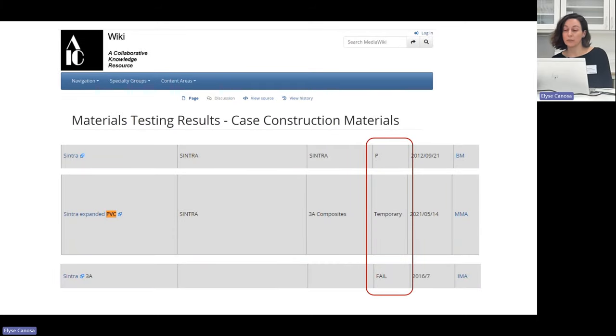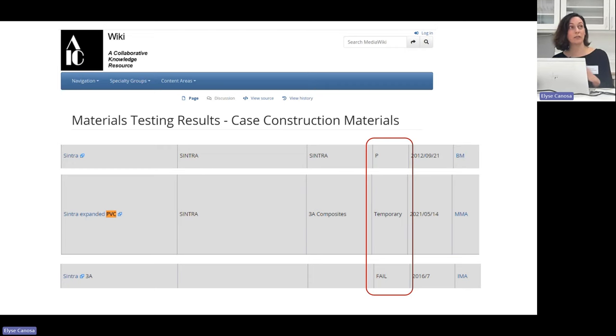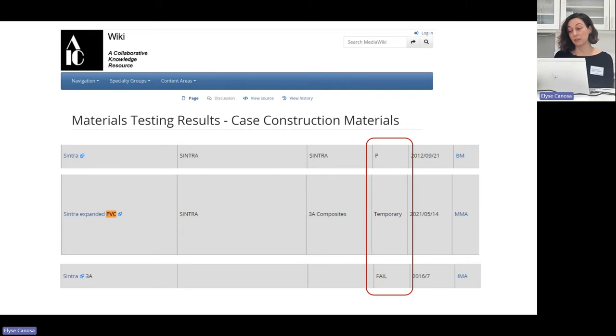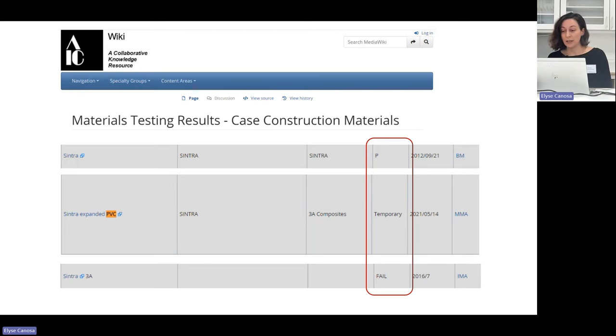In the AIC Oddy testing database, people have sent in results stating which institution it is, which material they've tested, and which procedure they've used. You can see there are some examples of materials that don't quite agree with each other in terms of their results. For example, a material called Sintra — a brand of expanded polyvinyl chloride without any plasticizers — has received results of pass, temporary, and fail from different museums and different protocols.